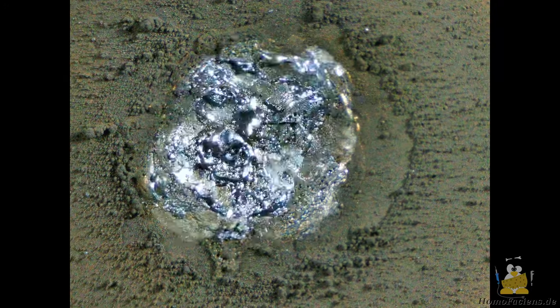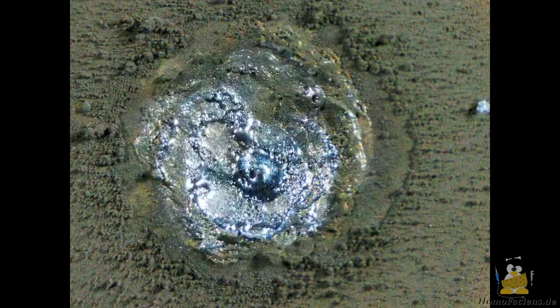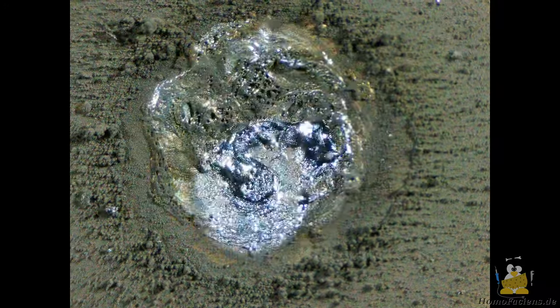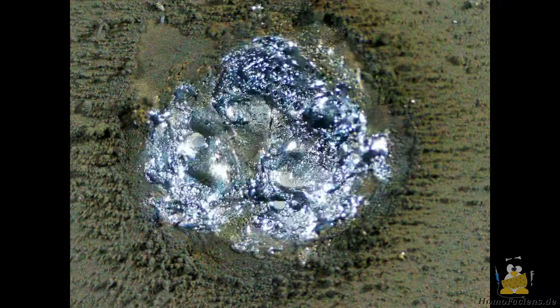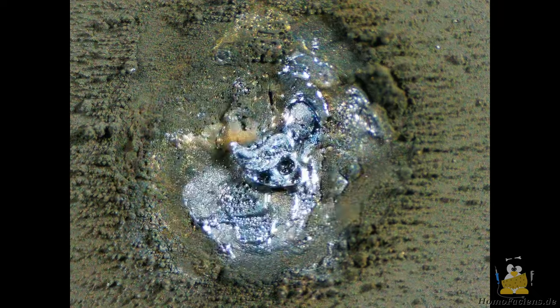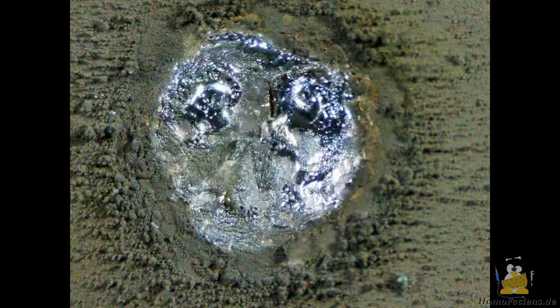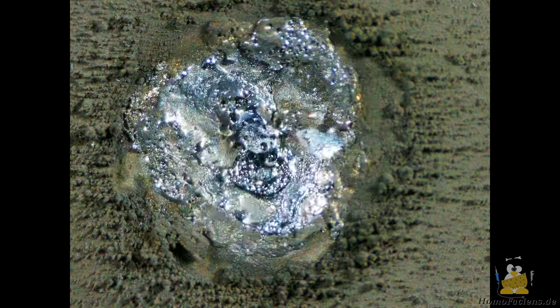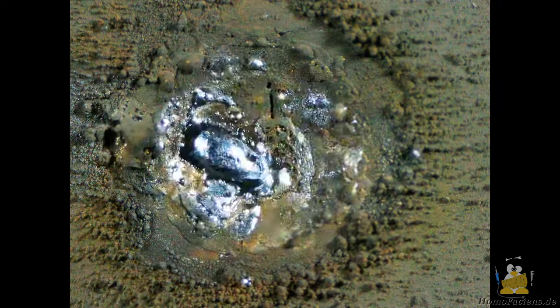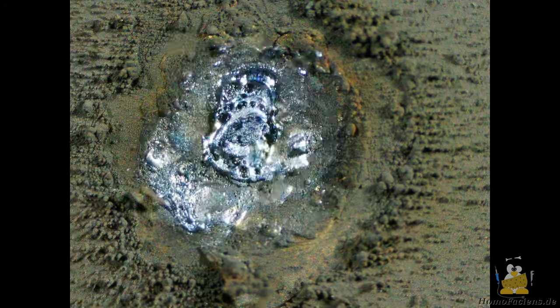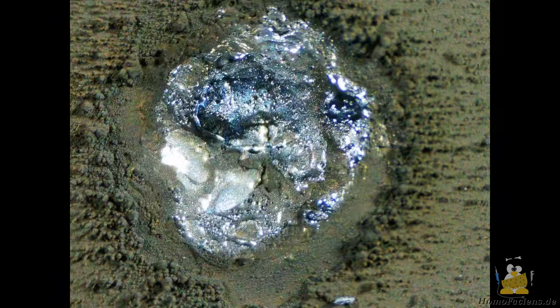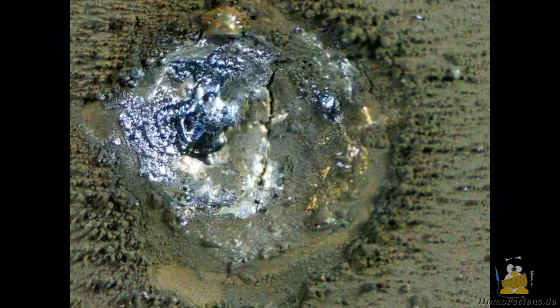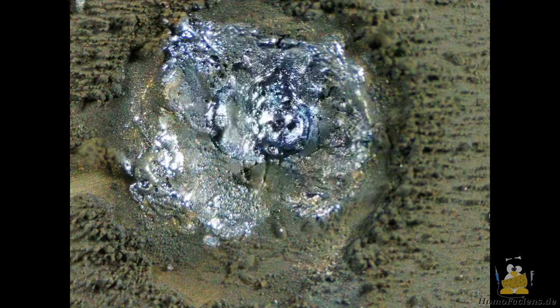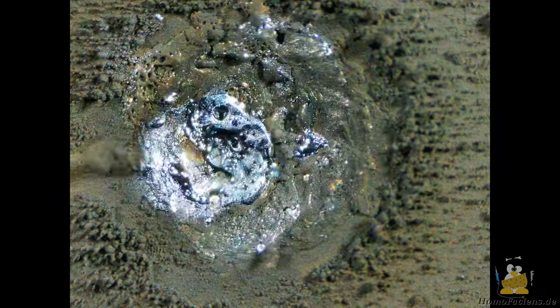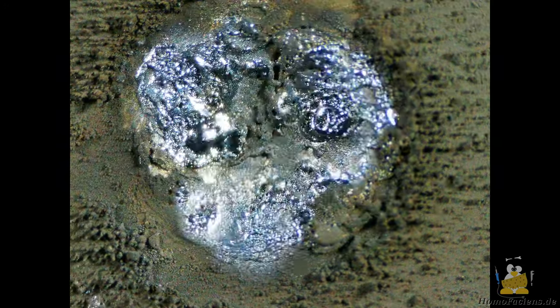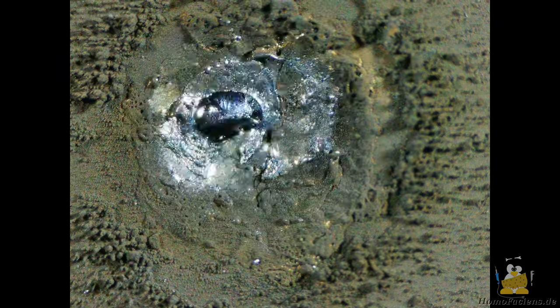This very fine dust contains various substances because steel does not only consist of iron. As already mentioned, many chemical and physical processes take place during spark erosion in air. The result is a grey-brown film that settles on the surface. It can be seen that during the drilling process, a crack forms in the center of the hole. Due to the constant melting and cooling, huge stress is applied to the material which causes the steel to crack.